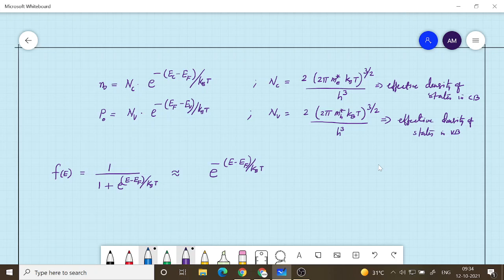Our logic for why this is a good approximation is that this quantity is very big when E is away from Ef. For example, when you are finding N0, E is some energy level in the conduction band. We are integrating all the energies in the conduction band, and Ef is the Fermi energy level, and we assumed that E minus Ef is many times larger than kBT. So in deriving the expression for N0 and P0 we have used an approximation. That approximation is called the Boltzmann approximation.